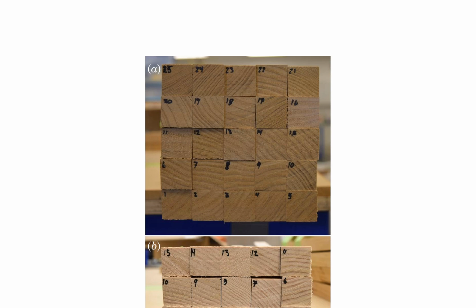This section of the research paper delves into the preparation of specimens for various tests, including longitudinal and transverse bending specimens, as well as single-edge notch bending (SENB) specimens. The preparation process began with planing boards down to a thickness of 25 mm using a grizzly planer, followed by ripping them on a sawstop table saw to create 25 x 25 x 410 mm longitudinal specimens parallel to the grain. These samples were then run back through the planer at 25 mm to reduce dimensional variability from the table saw before being cut to length on a DeWalt miter saw.